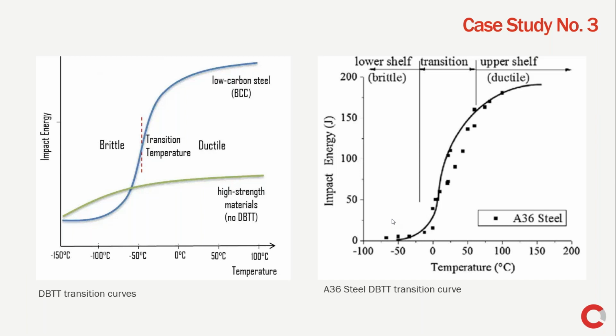And these are some of the curves that I was referring to, the DBTT transition curves. On the left here, this is just a schematic of how they look. Basically, some of the low carbon steels have a transition temperature around minus 50 Celsius. As the temperature drops, less energy is absorbed during the test, and then at some point the energy just drops significantly, transitioning to a brittle type of fracture. And we can determine the transition temperature for that particular steel.